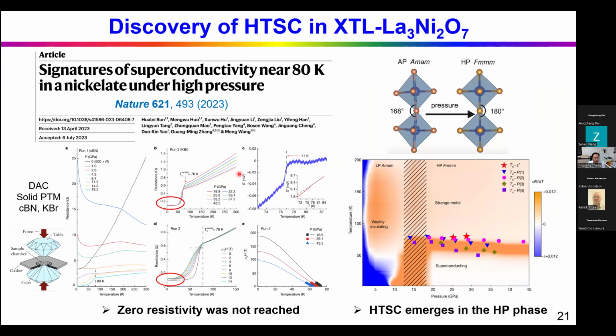So Meng Wang's group grew the single crystal, and then they performed the high pressure resistivity measurement by using a diamond anvil cell. They used solid pressure media, including cubic boron nitride and potassium bromide, two different solid pressure media. They found that above pressures of about 14 gigapascal, they can observe a clear resistivity drop. And depending on the pressure medium, this drop can be quite sharp. And this drop can also be suppressed by applying a magnetic field.